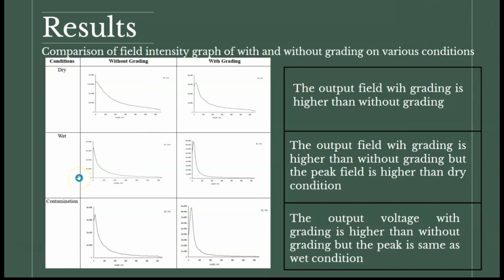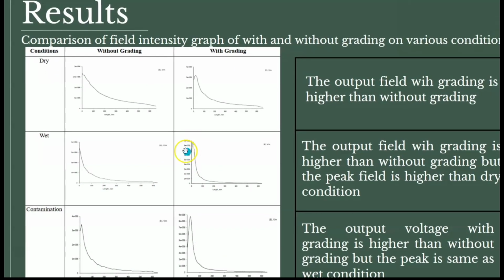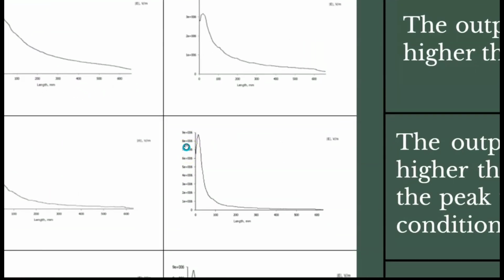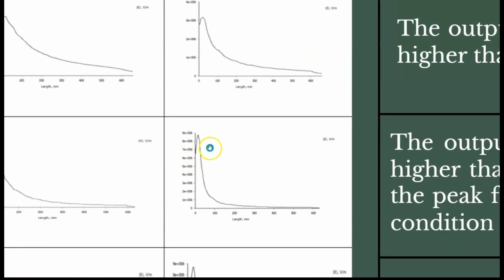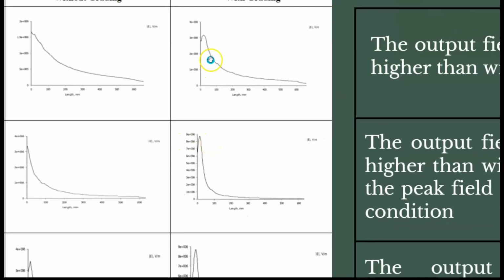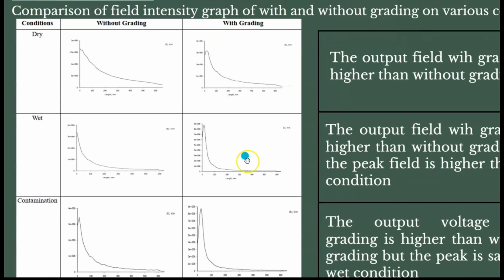And for the wet condition, the output field with grading is higher than without grading, but the peak field is higher than the dry condition. So here we can see that the peak is about 8 exponent 6 to 9 exponent 6 volt per meter, while the dry condition is about 3 to 4 exponent 6 volt per meter.